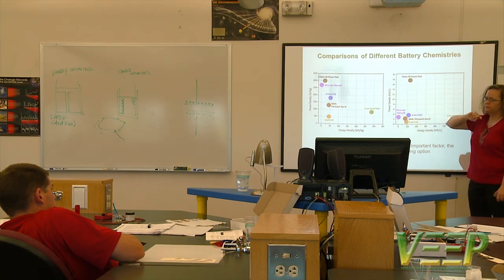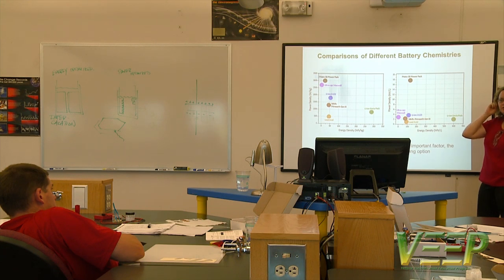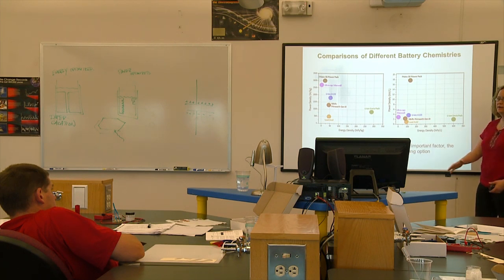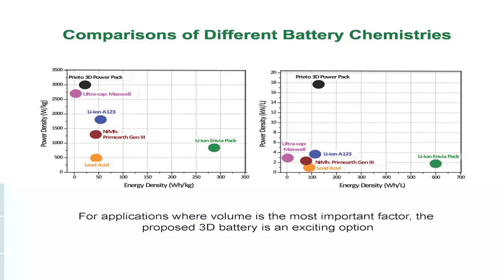We get this power density for two reasons. One, we use an anode material that stores a lot more lithium per unit volume than graphite does. It's also a lot safer. But also, because we electroplate, we don't have to add all these binders and excess mass that batteries typically use. And so we've gotten rid of a lot of the inactive mass that doesn't store lithium anyway. And so we can store a lot per unit volume.